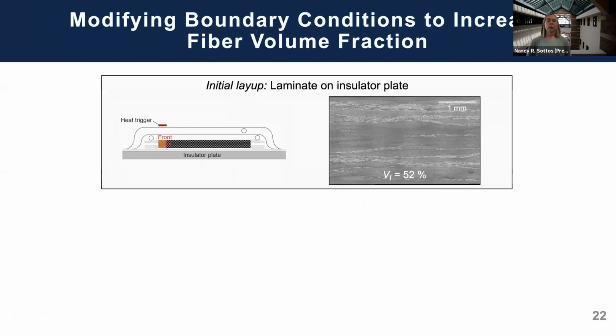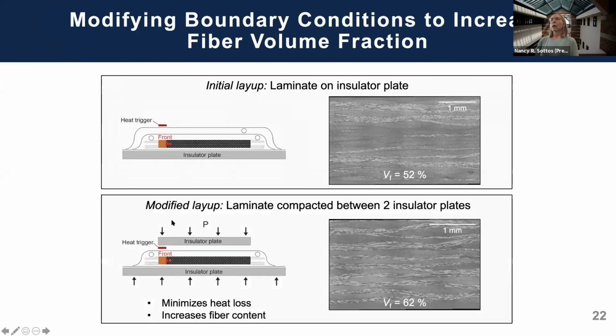All right. In order to get volume fractions up and address these issues with increasing fiber volume fraction, we thought a lot about how to modify the boundary conditions to get to higher volume fractions. So our initial layup was, as I described before, that led to volume fractions of about 52%. And we've done a lot of work to modify this using insulative plates. So the lamina is compacted between two insulator plates. And we actually also add some compaction pressure to our process. In the prior example, we weren't doing any compaction.